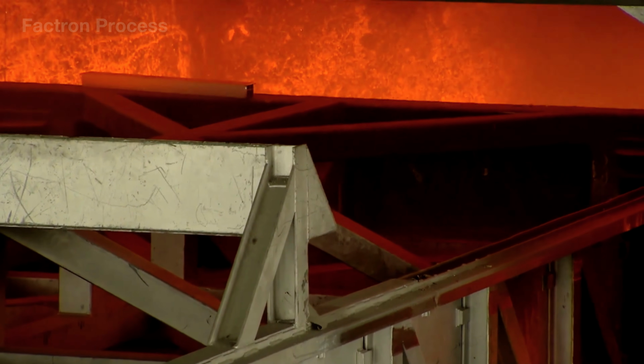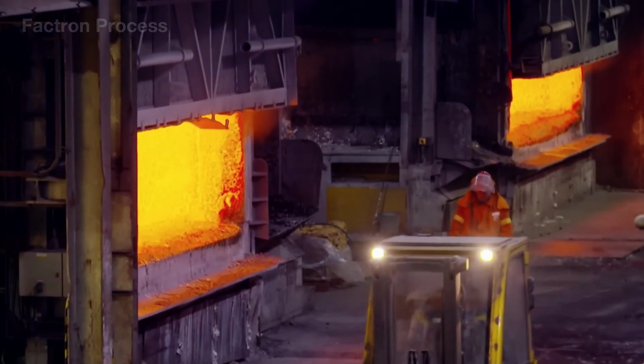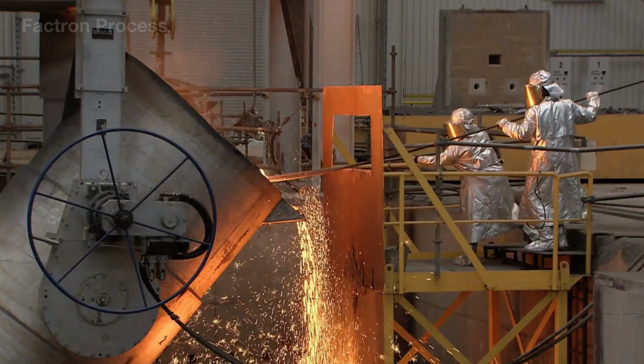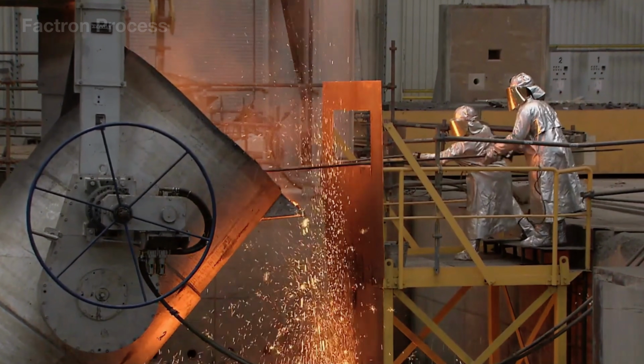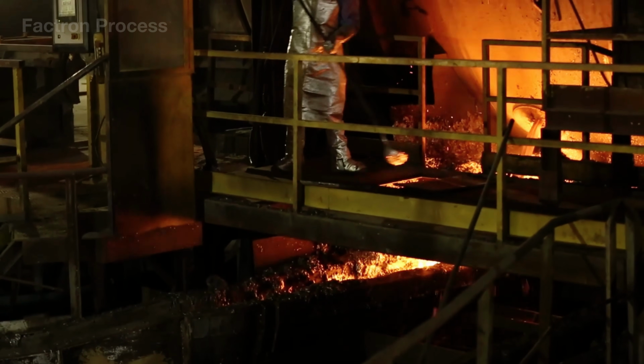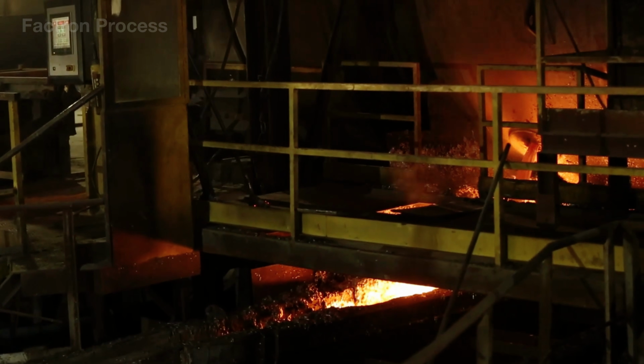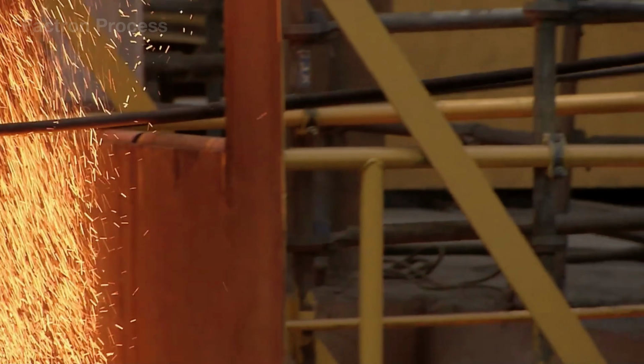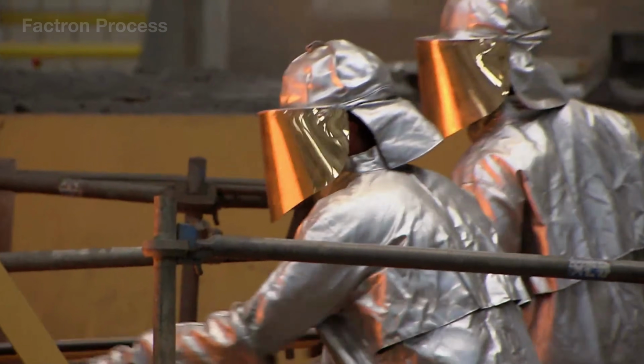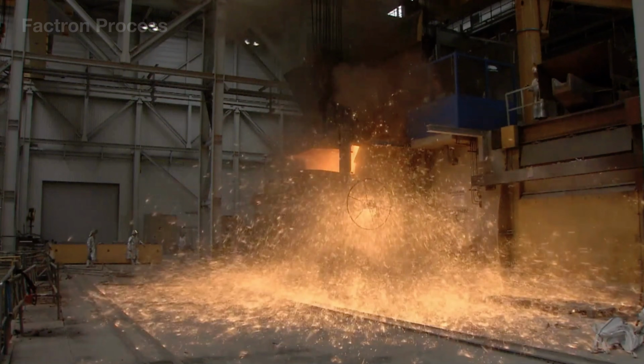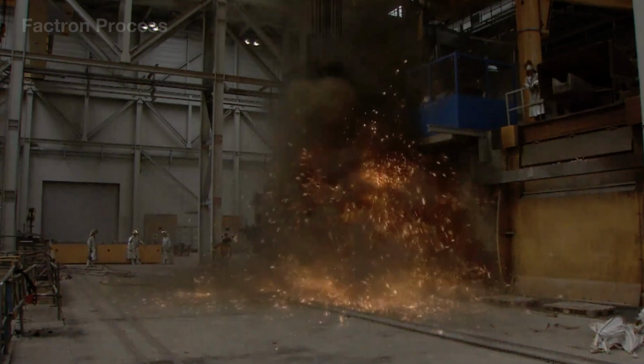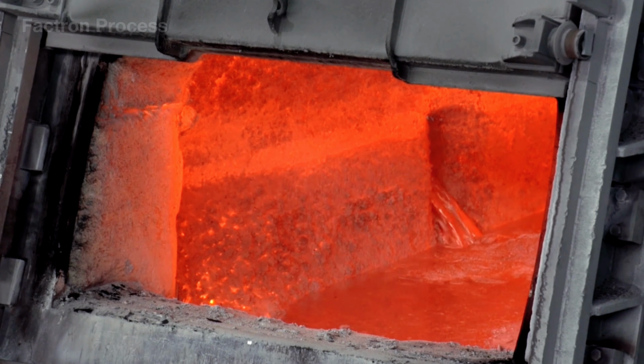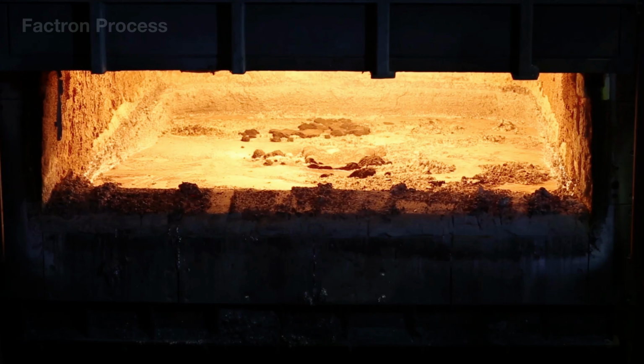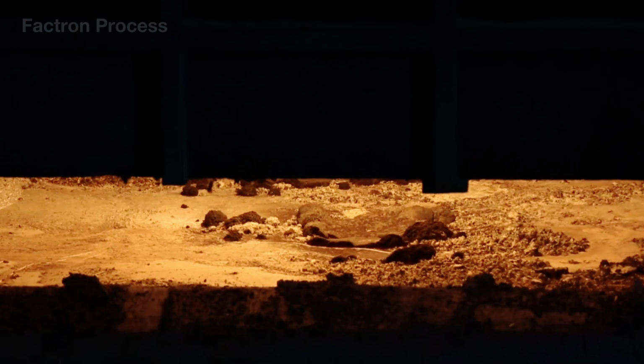The molten aluminum is then degassed to remove hydrogen and microscopic gas bubbles that could create internal porosity in the finished product. Samples are also taken directly from the furnace for chemical analysis before the metal is approved for casting. Compared with producing primary aluminum from bauxite ore, recycling aluminum requires only a fraction of the energy. As a result, the skin that once enclosed an aircraft weighing tens of tons can be melted down and returned to industry as new metal stock, instead of becoming waste.